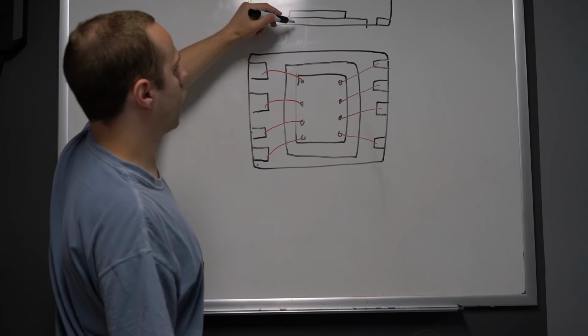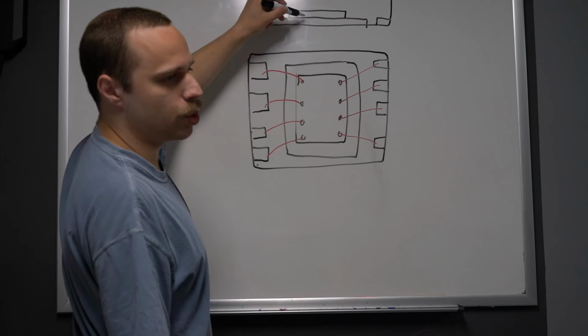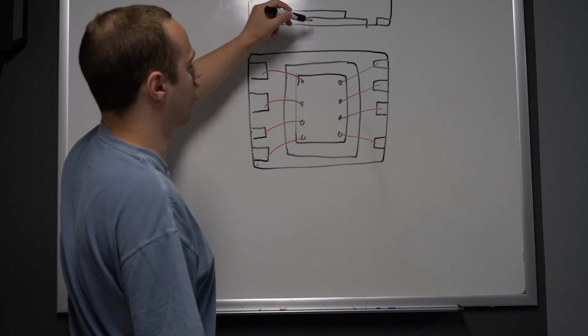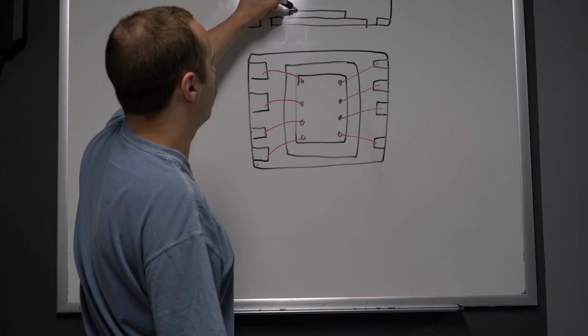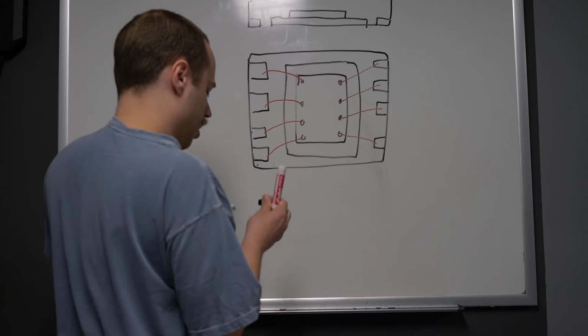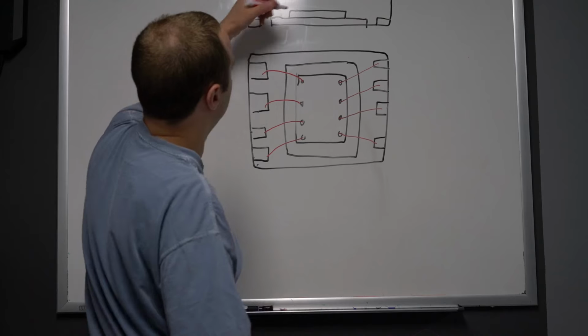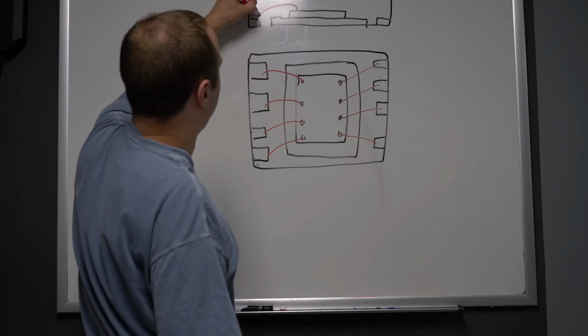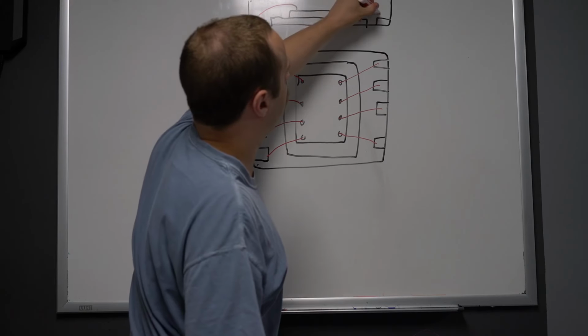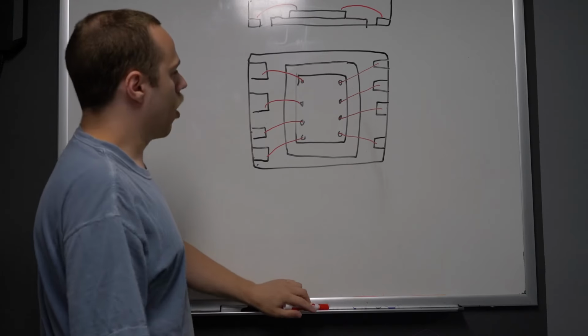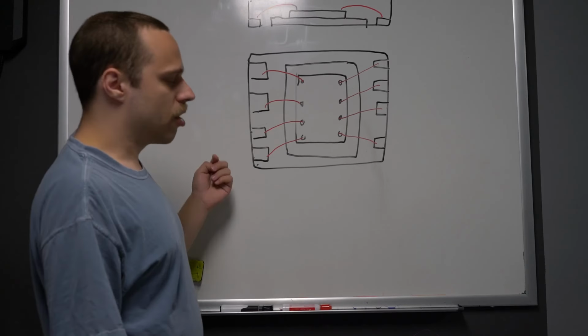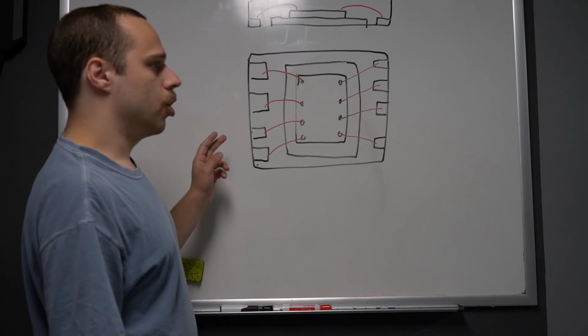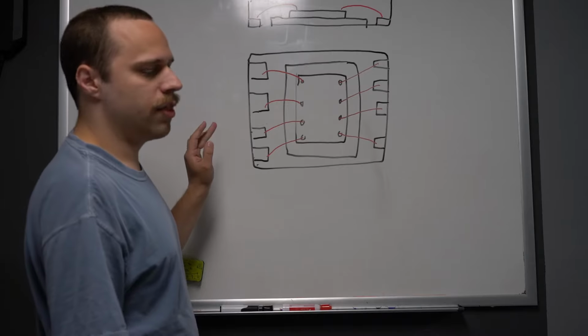attached to the paddle by some sort of conductive adhesive. Usually it's an epoxy with silver particles filling inside it. And then we have the wire bonds, which I'm going to do in red to stay consistent. So the wire bonds are going to come out from here and out to here. And in order to get a better understanding of how the device is put together, we can do a mechanical cross-section of the device.